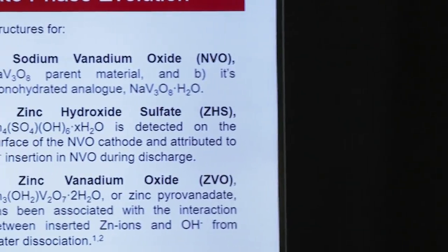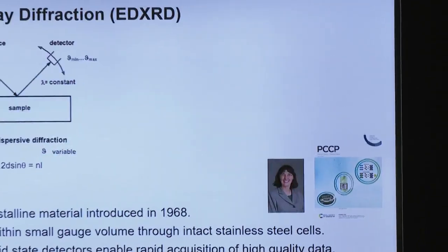There are several phases that are formed. I show them here. There's the parent phase. Then we have zinc hydroxide sulfate. Zinc hydroxide sulfate is important because that told us that actually there's a pH change taking place inside the battery. What's happening is that there's proton insertion. The electrolyte becomes more basic, and we precipitate a solid. And then zinc vanadium oxide is a zinc insertion material.